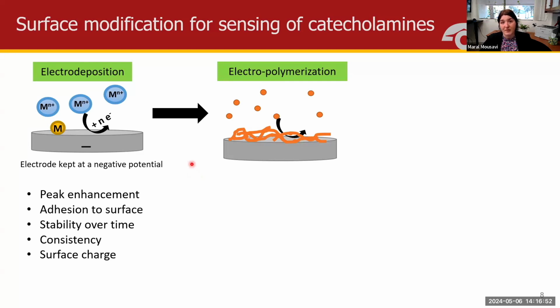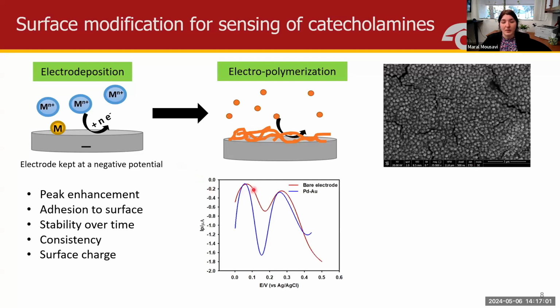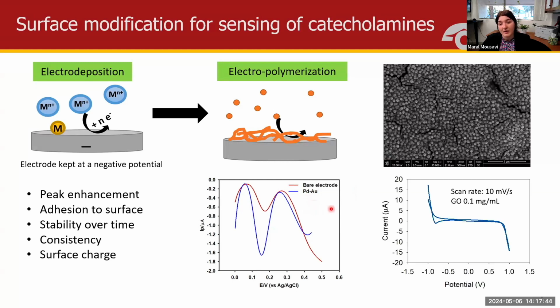to maximize surface area. So the first step, we've actually optimized, is electrode deposition of metal nanoparticles. As you notice, as we do electrode deposition of metal nanoparticles, we can increase the peak for catecholamines. So post modifying the surface with nanoparticles, which enhances the surface area initially, we modify the surface again using electropolymerization. So we polymerize EDOT at the surface. We're creating a coating of PEDOT:PSS.